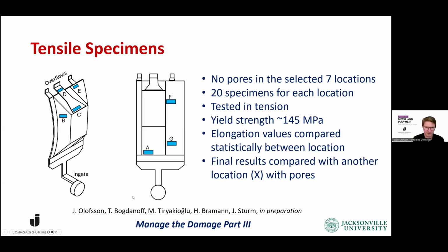What we're looking at is a high pressure die casting, as you can see schematically here in the picture. In order to evaluate the local material properties and see how they vary throughout the casting, we have done tensile testing at several different positions of this casting, labeled here A, B, C, D, E, F, G. For each location, we evaluated 20 specimens, tested in tension. The yield strength of this material is around 145 megapascals. As Murat just mentioned, the ductility potential will be around 27% for this material, I think was the value.